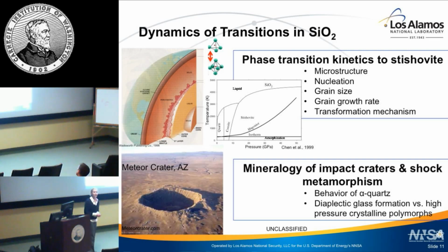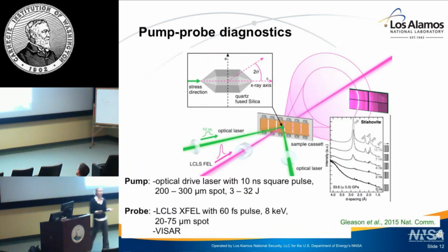It is essentially a pump probe experiment that we execute. Okay, here I show a schematic of our setup. In the center is our sample cassette, so our SiO2 samples. We come in on the left-hand side, where I show in green the drive laser. The spot that is ablated on our sample, which aids the generation of the shock front, is always larger than our X-ray probe, right?